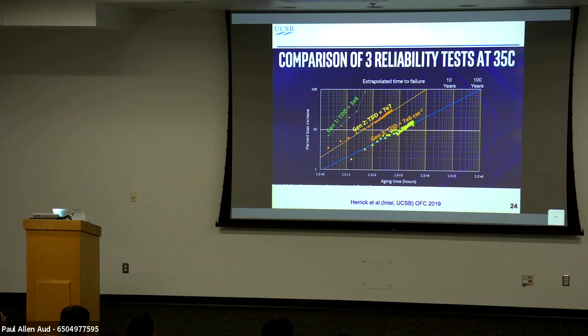This is, again, some of Intel's data on our devices, but it just shows the impact. When you have 3×10 to the 8th dislocations, the lifetime is a few thousand hours. Get it down by 7×10 to the 7th, you get up to a few years. You get down to 7×10 to the 6th, and you're pushing a 100-year lifetime. That's fine for room temperature, but not good enough for real reality. So you have to look at what happens when you age it at higher temperatures, and everything gets much worse. There's a real temperature acceleration factor here.